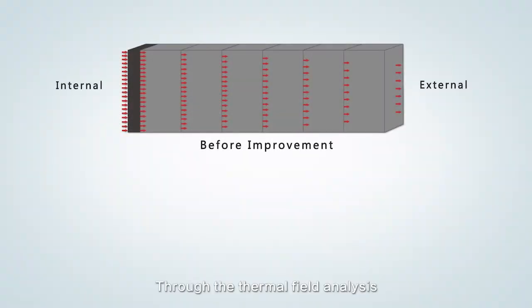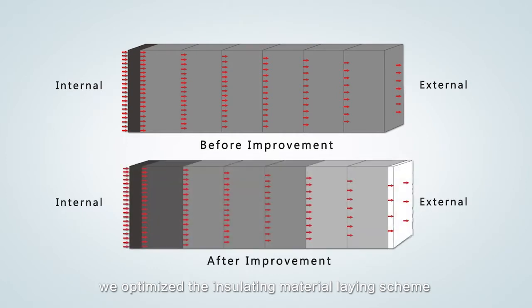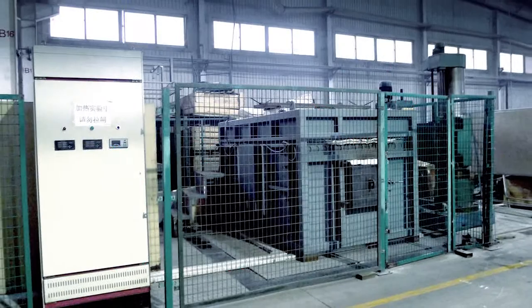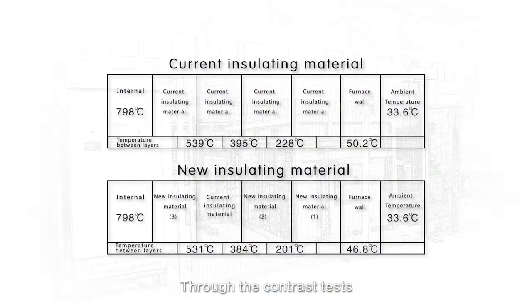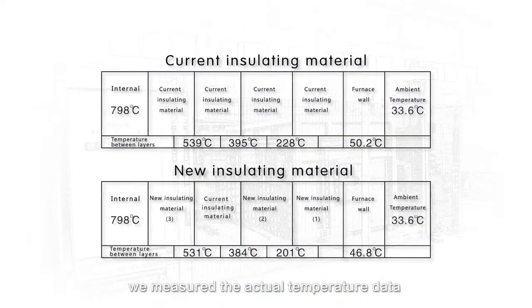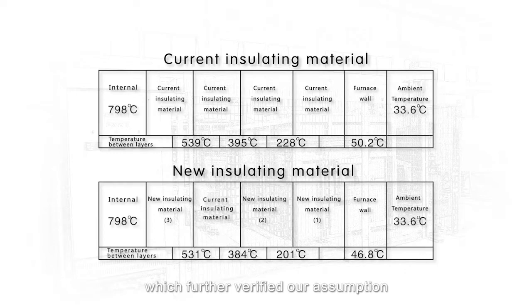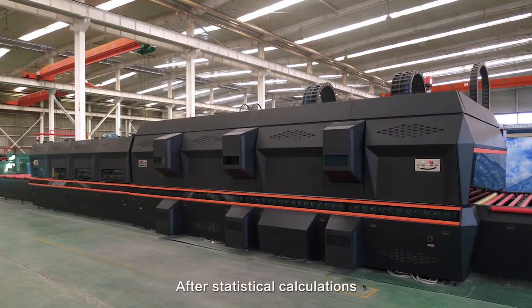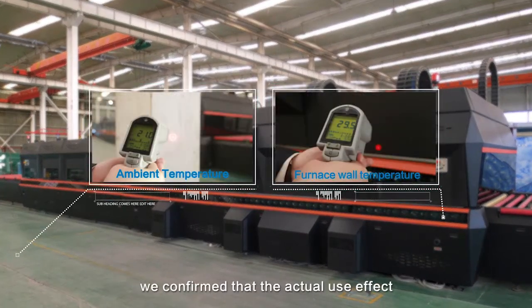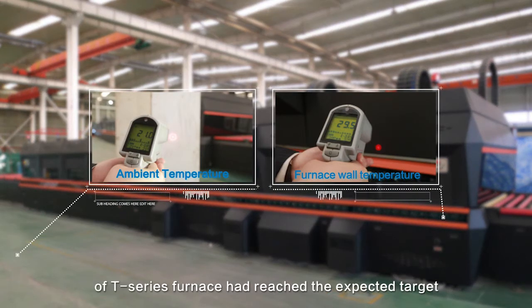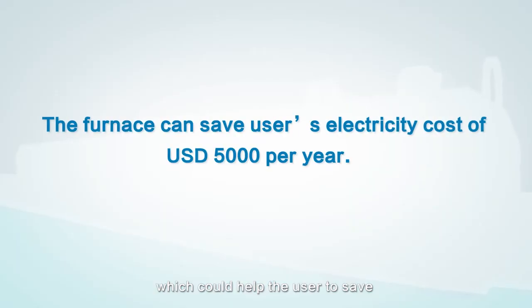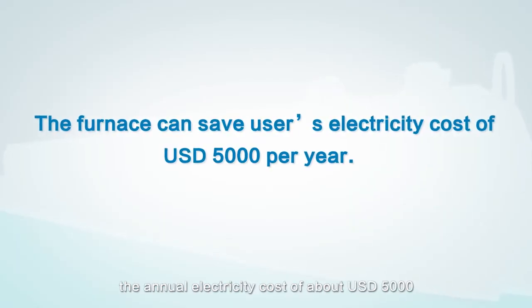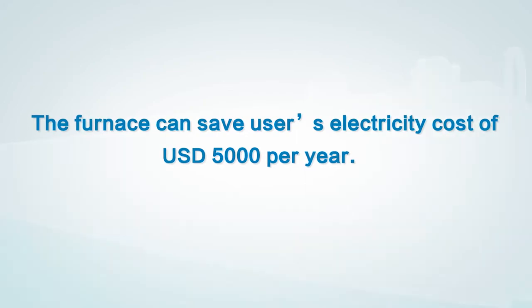Through thermal field analysis, we optimized the insulating material laying scheme with different performance layers, thus maximizing the heat insulating effect. Through contrast tests, we measured the actual temperature data, which further verified our assumption. After statistical calculations, we confirmed that the actual use effect of the T-Series furnace had reached the expected target, which could help the user save an annual electricity cost of about $5,000.